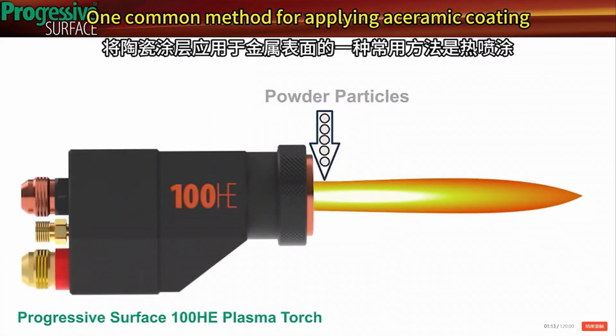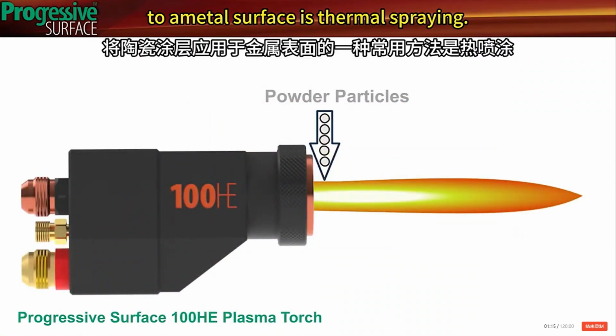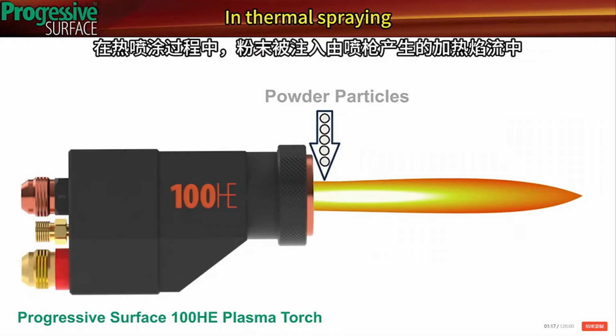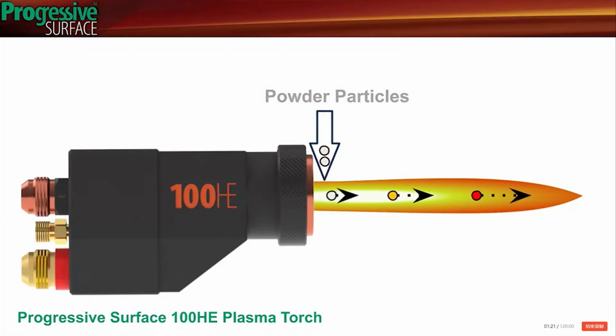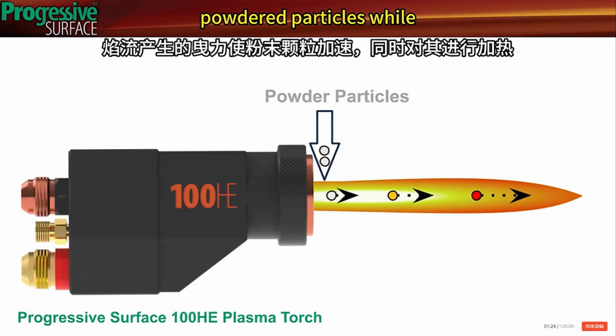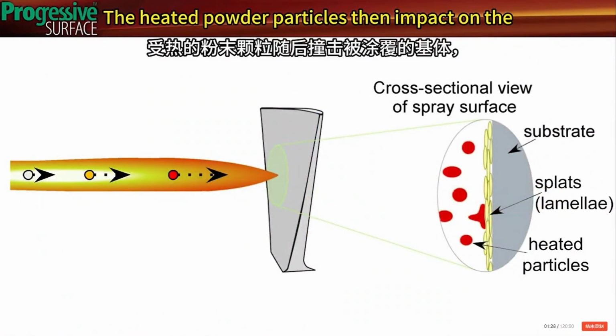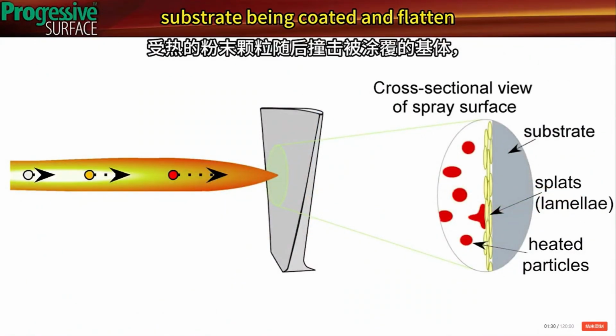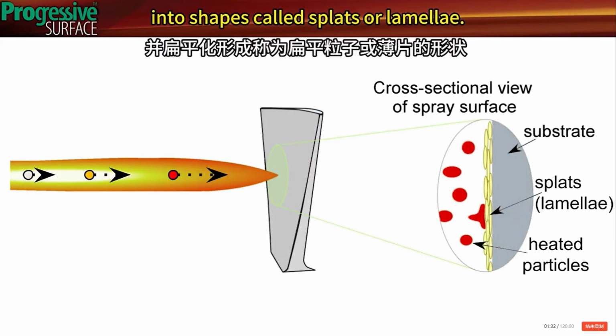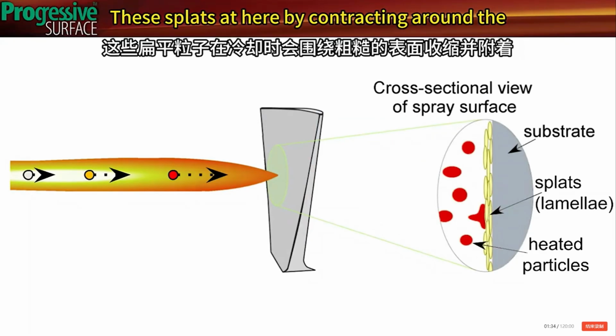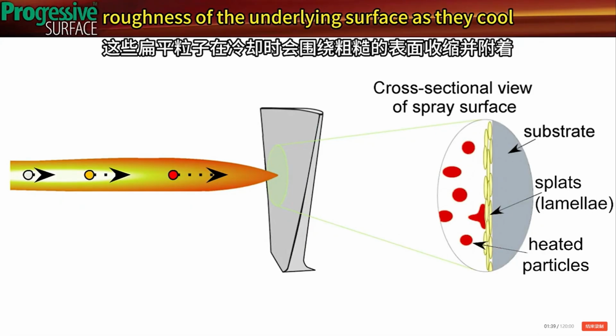One common method for applying a ceramic coating to a metal surface is thermal spraying. In thermal spraying, a powder is injected into the heated plume produced by a torch. Drag forces from the plume accelerate the powder particles while simultaneously heating them. The heated powder particles then impact on the substrate being coated and flatten into shapes called splats or lamellae. These splats adhere by contracting around the roughness of the underlying surface as they cool.